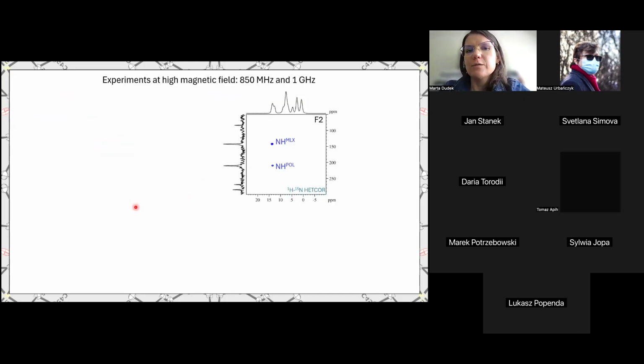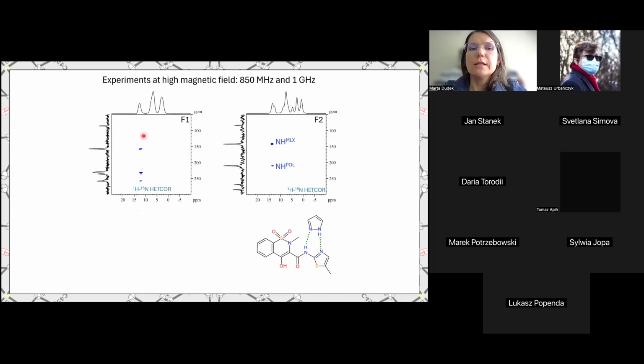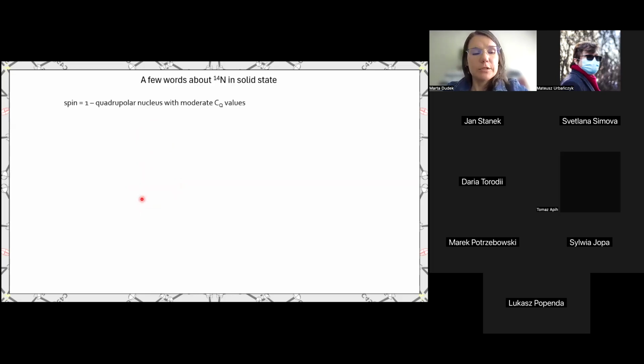So finally, these are the experiments performed at the University of Warwick. To have a final confirmation, we registered a two-dimensional proton-detected nitrogen-15 and nitrogen-14 NMR experiment. And as expected for Form 2, there was nothing suspicious, again confirming the diffraction-derived crystal structure. And for Form 1, we indeed saw 4 correlation signals corresponding to 4 different sites in this crystal, again confirming this 0.7 to 0.3 ratio.